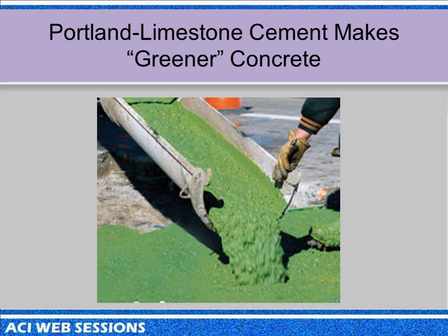Standard tests, if you do an ASTM C1012 test at room temperature, you don't see this. So we decided, in the interest of passing this thing and getting limestone cements in our standard, we'd say not for sulfate resistance at this time. That same restriction applies to mineral fillers, like if you're using limestone fillers in the concrete as well.